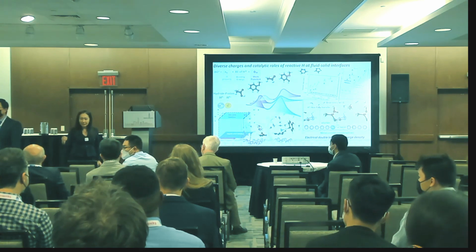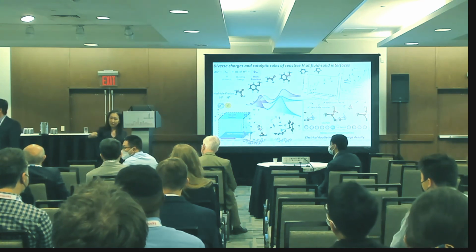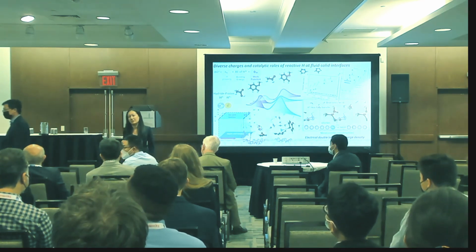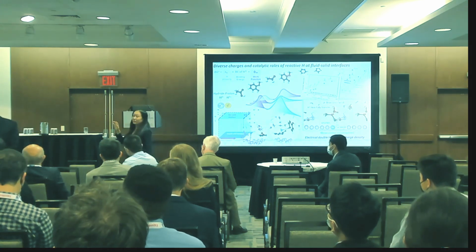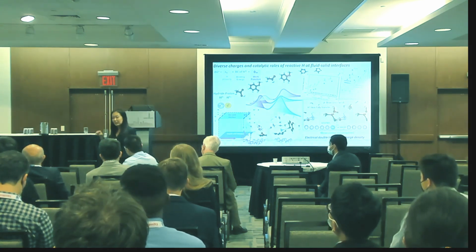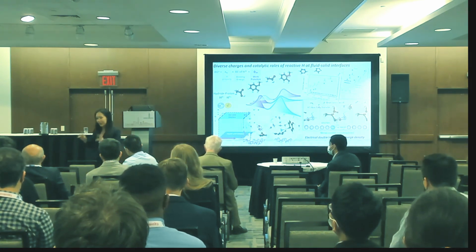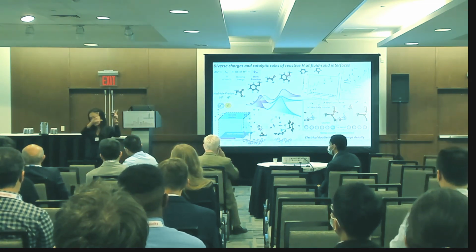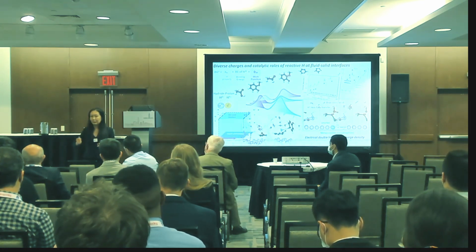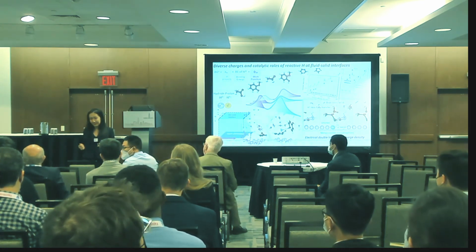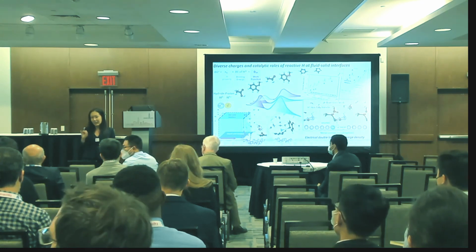So it indicates that the solid surface actually has a way to stabilize the transition state. And this is something we are studying, how the reaction happens at the interface. The same acid, homogeneous and on the surface: the one on the surface has a higher rate, because the surface actually plays a role.